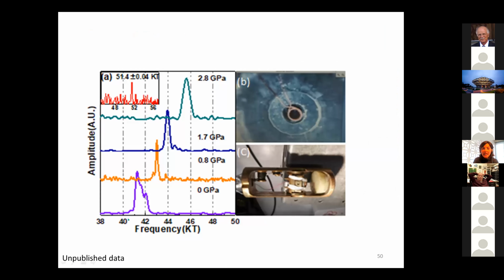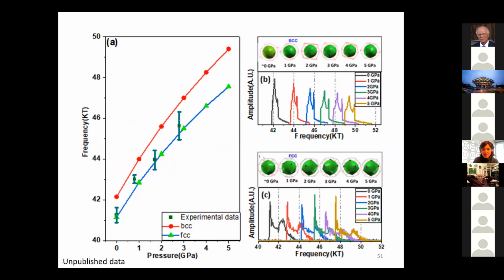What we see here is that as we increase the pressure, to what most of us think is very low pressure, we see a nice shift in the location of the peak. We are comparing this: the dark green data is the experimental data, and the light green and red are the theoretical predictions for BCC and FCC. Our data is very close to the location of the FCC peak as it shifts. So we think the ground state structure of lithium at very low temperatures, 300 milli-K, is closely related to the FCC structure based on this observation. It's more than just the exact value, because that's less relevant; it's how the trend changes, BCC versus FCC, that makes us think this is more closely related to FCC.